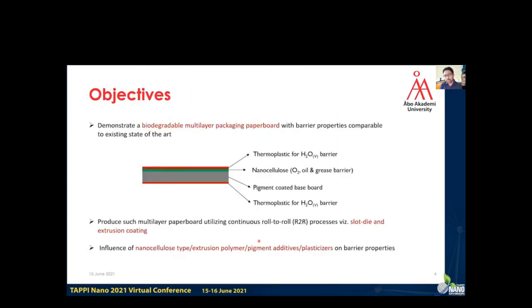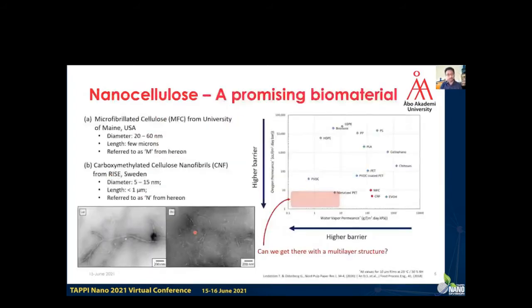That brings us to the objectives of this work, where we wanted to demonstrate a biodegradable multi-layer barrier packaging paperboard with properties comparable to state-of-the-art. So the concept is that we start with a pigment-coated baseboard and then have nanocellulose on top of it as an oxygen, oil, and grease barrier, and a thermoplastic layer on the top and bottom to protect it from moisture. And also, we wanted to produce this multi-layer paperboard using continuous roll-to-roll processes such as slot die and extrusion coating. And then we looked at the influence of nanocellulose type, extrusion polymer type, and pigment additives and plasticizers on the resulting barrier properties.